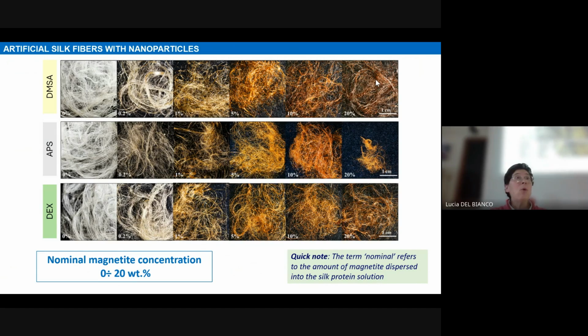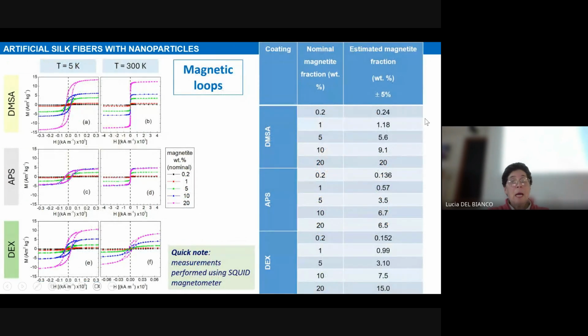And then started our magnetic characterization, which was quite demanding because, of course, we have a lot of samples. And the first thing we measured, I show a selection of the results to you. So first of all, magnetic loops. We use a SQUID magnetometer, which is a very powerful instrument, very suitable for this kind of investigation, that is here in this department. And we measured the hysteresis loop at 2 different temperatures, 5 and 300 Kelvin. The first information that we got from this measurement was to estimate the real fraction of magnetite in the fiber, which not necessarily was the same as the nominal magnetite fraction that we put in the solution.